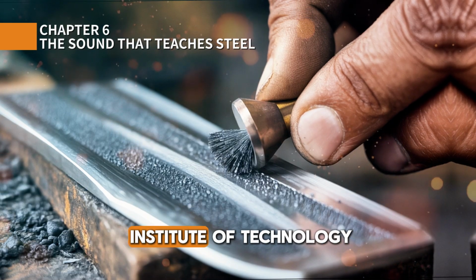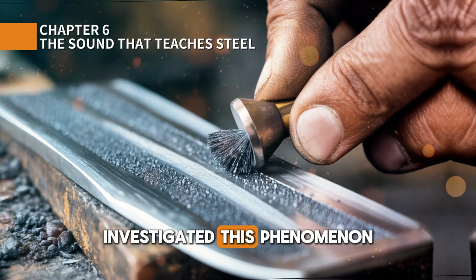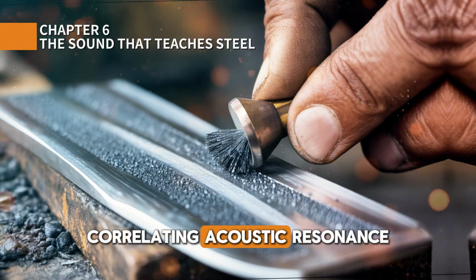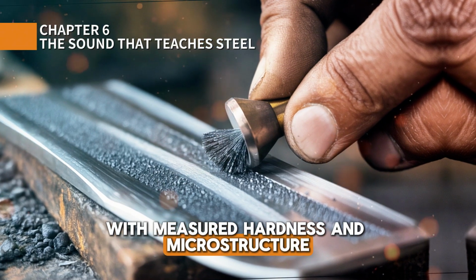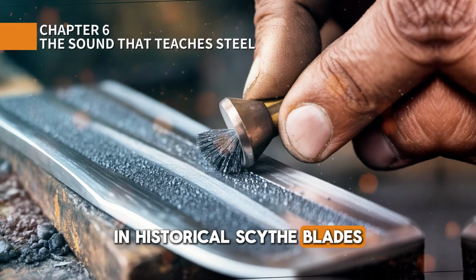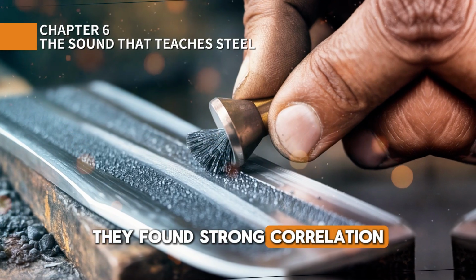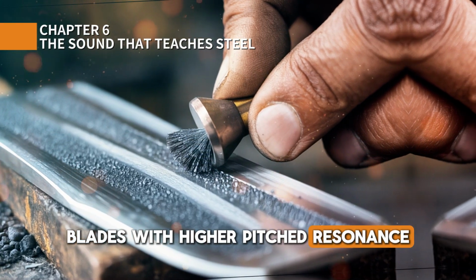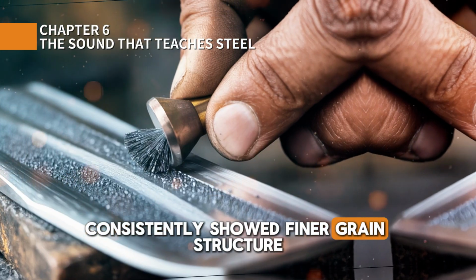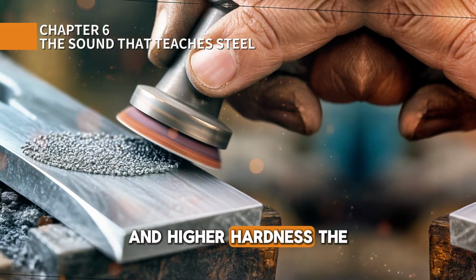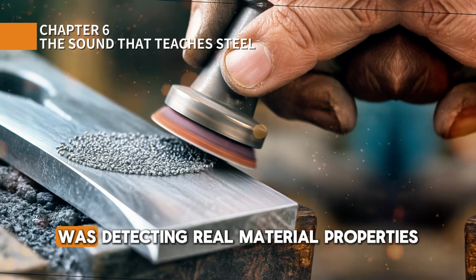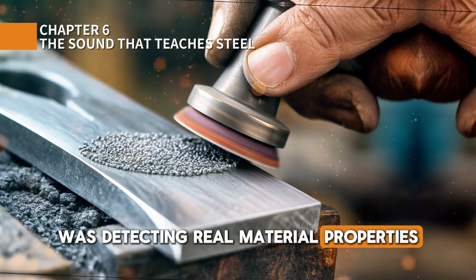Researchers at the Karlsruhe Institute of Technology investigated this phenomenon, correlating acoustic resonance with measured hardness and microstructure in historical scythe blades. They found strong correlation. Blades with higher pitched resonance consistently showed finer grain structure and higher hardness. The traditional acoustic assessment was detecting real material properties.